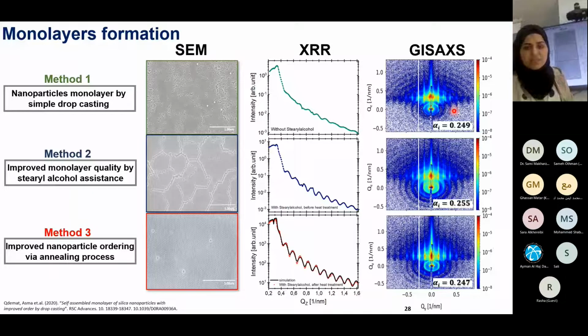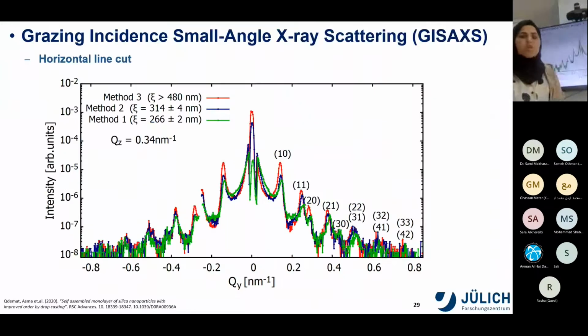Also, the diffuse rings become weaker, which is an indication that most of the particles take part in the ordering, and the scattering from a single nanoparticle is strongly suppressed. In order to compare all these GISAXS patterns together, it is easy to perform a horizontal line cut at this position, exactly at the Yoneda line. From the horizontal line cut we can see that the monolayer, the red line obtained in method 3, has higher intensity, which is due to the long-range order.